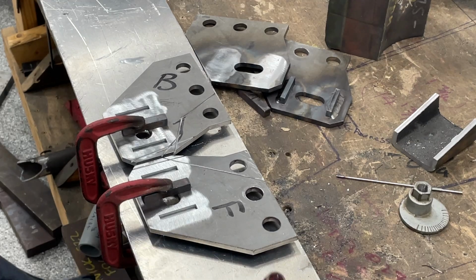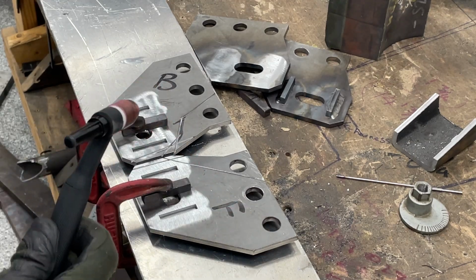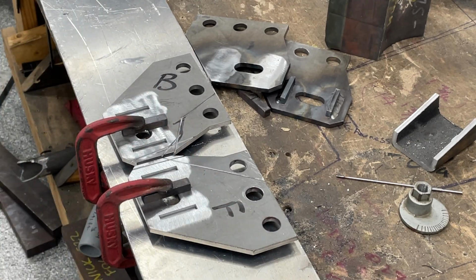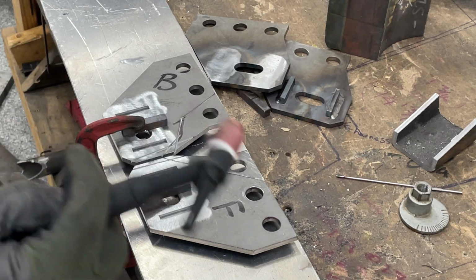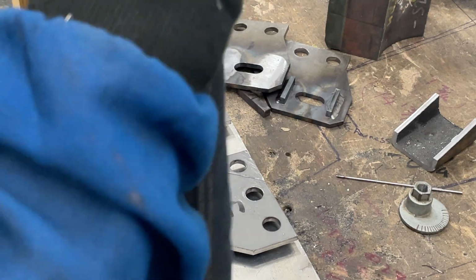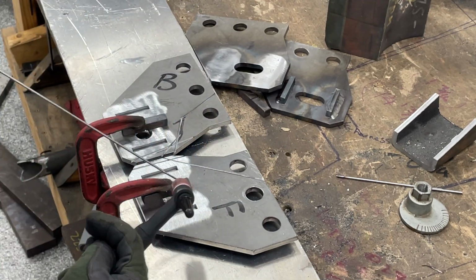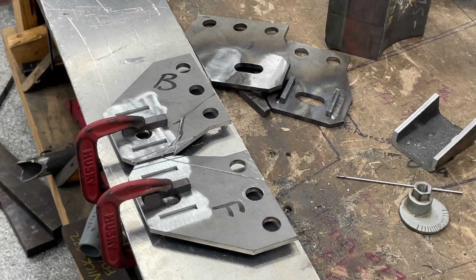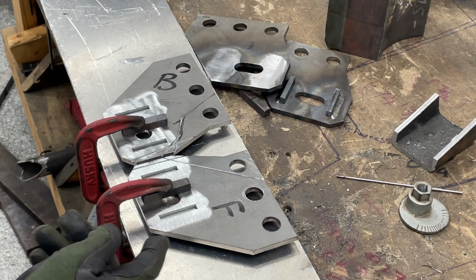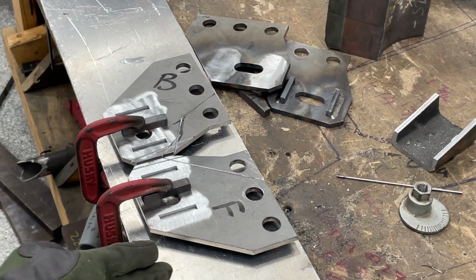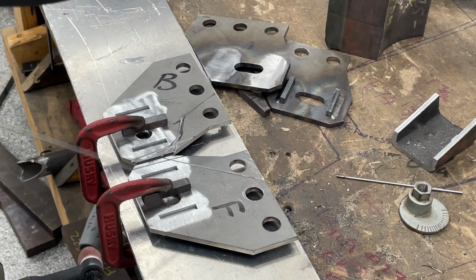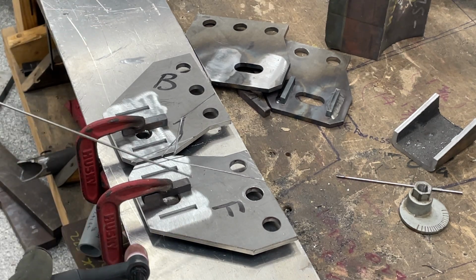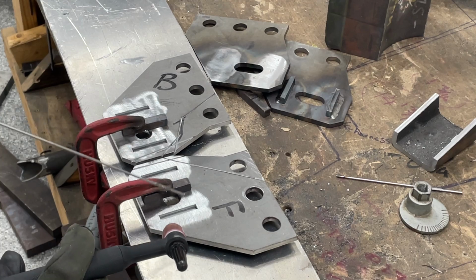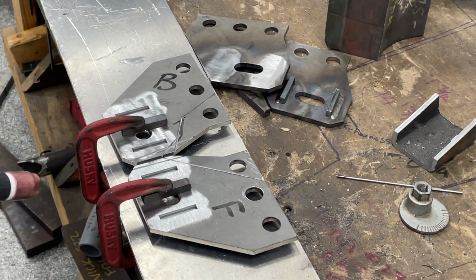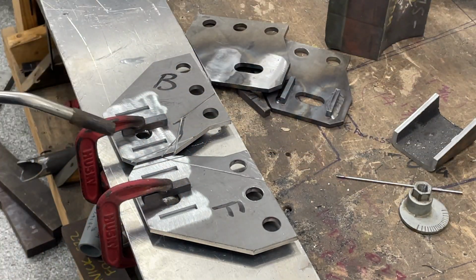I am using a number 8 gas cup. I'm welding with ER70S2. Nothing crazy. I do not need a high strength wire for this because I'm going to be doing so many passes on this weldment, and because of the joint type, there's going to be a lot of dilution or base metal stirring and pickup that I can rely on for strength inside the weld. To prevent these tabs from bending outwards too far, you can actually choose your bead sequence on where your weld beads go first with respect to distortion.